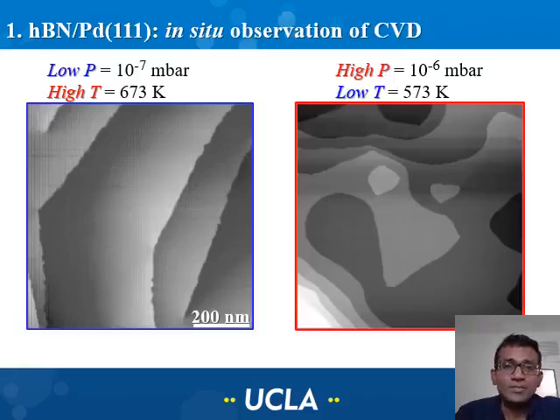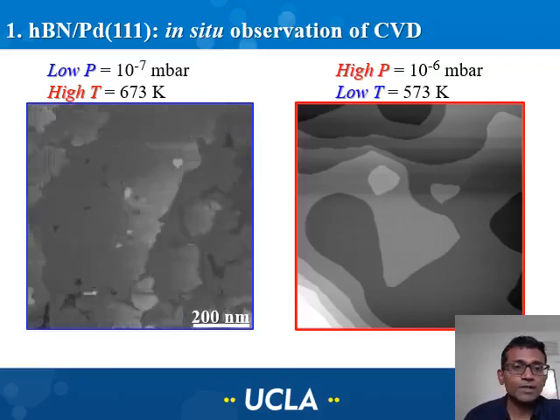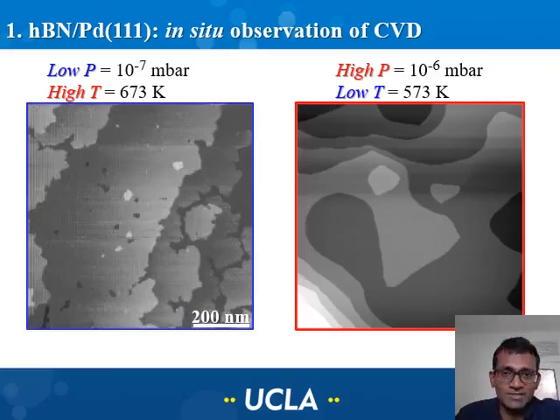Okay, so these are typical scanning tunneling microscopy images that are acquired as a function of deposition time at two different conditions. What you're watching is time-lapsed images acquired from the same field of view from a bare palladium-111 upon exposure to what we call relatively low partial pressure of borazine, and at what we consider, in this experiment, a high temperature. And what you have observed is, starting with atomically flat terraces, we observe island formation followed by a complete monolayer